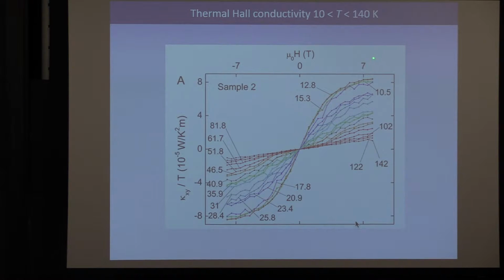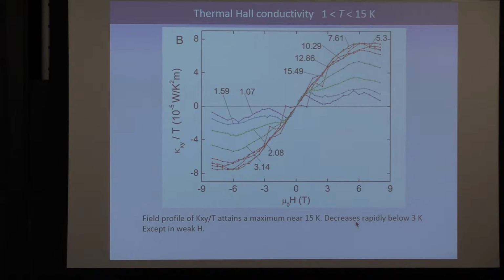So it reaches a maximum kappa XY at about 15 Kelvin. Then when you go to lower temperatures, it starts to come down again. And at the lowest temperature, here's 1 Kelvin, it has some action around 2 Tesla that remains to be sorted out.